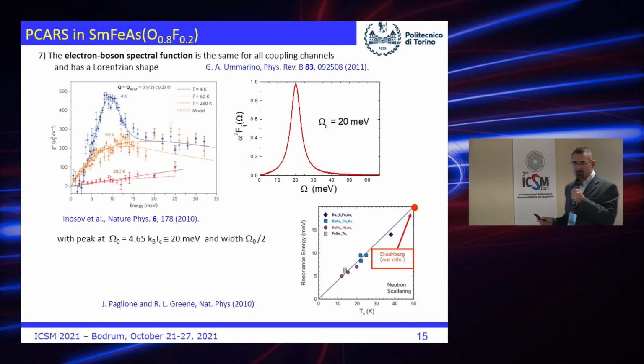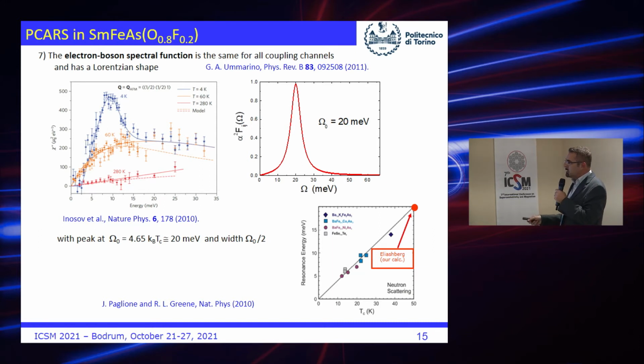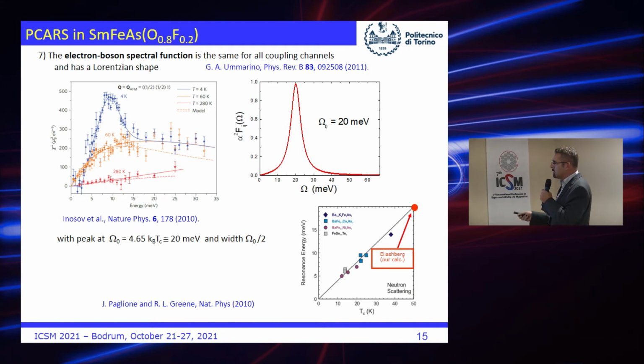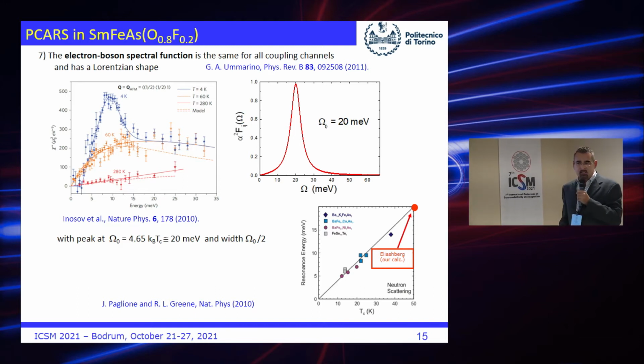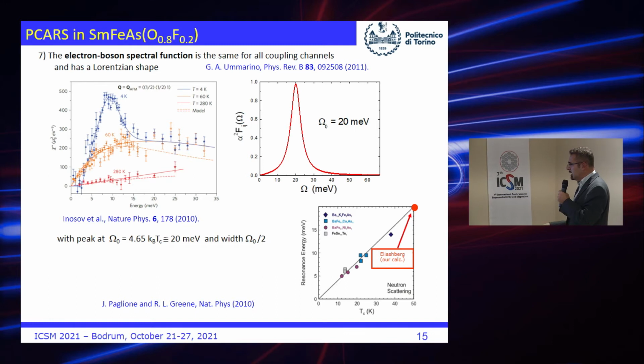This was not obvious, because in the normal state it has a completely different shape. So this resembles a Lorentzian. We chose the spectrum to have a Lorentzian shape with a certain maximum at a given energy. What is the energy? Well, we know from the scaling law of the spin resonance energy with respect to Tc that if we want 50 Kelvin of Tc, we can choose an energy of about 20. So we will choose this as 20.